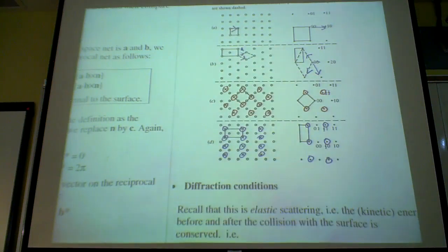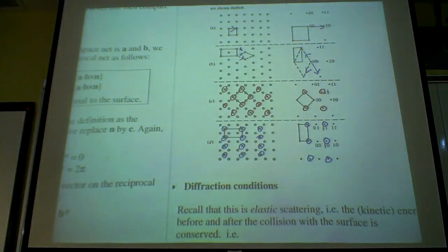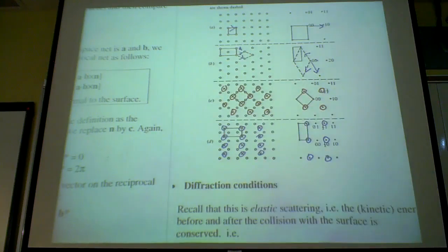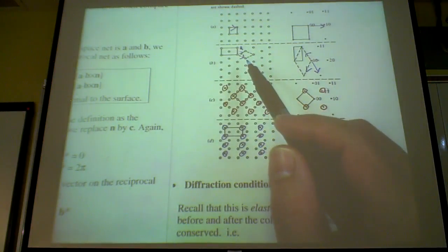If you populate a monolayer of sulfur atoms on top, they can also arrange in a pattern, because depending on the energy they can achieve, they always go into the same local site. So if some atom prefers the four-fold hollow site, then you populate all the four-fold hollow sites that way. Then your adsorbate will generate another periodicity, isn't it? Because it would then generate a two-dimensional geometry on top of your original substrate.